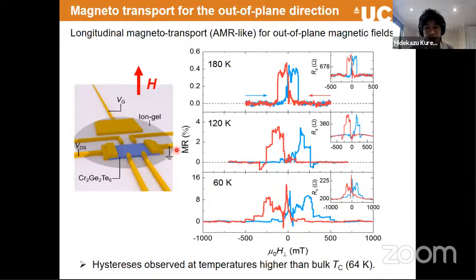So this is the transport resistance measurement, or the Rxx measurement, when we apply the magnetic field out of plane. We show the 60 Kelvin results. It showed a nice hysteresis that guarantees the magnetism. And we go up to 120 Kelvin, and if we go up to 180 Kelvin, we can still maintain the hysteresis. That strongly suggests that this material is still magnetic at a temperature of 180 Kelvin, which is very different from the Curie temperature of 64 Kelvin for the bulk or undoped system.